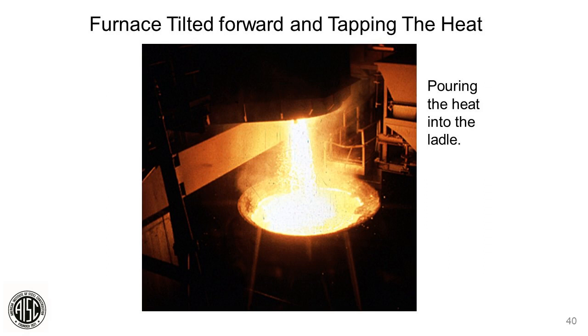But if you look at the iron-carbon phase diagram, once you get above 0.76, you're in a whole different world with carbon and strength and microstructure. So our world is 0.76 carbon and down. Typically structurals are 0.20 carbon and down. Once you get into 2% carbon, you're into cast iron. There's so much carbon, you basically make supersaturated iron grains with graphite flakes. As we all know, cast iron plates are kind of hard, but they're very, very brittle. So we stay in the steel world, 0.76 and below. Above 0.76 is called hypereutectoid, and that's a world I don't even live in. So everything we look at is 0.76 and below, and it's microstructure as a function of carbon content.